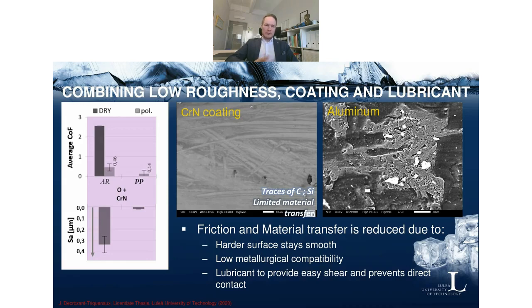But post-polishing, so removing defects on the chromium nitride coating and retaining the lubricant, can reduce friction even more, like 3 times lower friction with post-polishing and lubricant. You can notice the lower curve shows the Sa value of the surface for the chromium nitride. So you have about 0.3 for the as received and 0.03 or so for the post-polished.